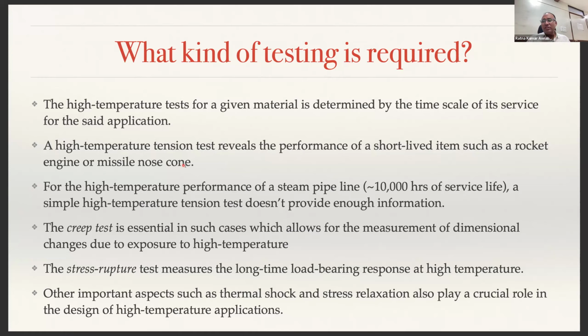However, for example, if you are dealing with a boiler, in the boiler you have a steam pipeline, right? And this steam pipeline is subjected to this high temperature for an extended period of time. Typically, you design these boiler pipes for 10,000 hours of life. Very long period of time. So that means it is subjected to constant temperature and constant load over such a long period of time. Then doing a simple high temperature tension test will tell you only what the strain is at that particular temperature. You are not waiting to see what is happening with relaxation and all these things. So that will not provide enough information. If you do a high temperature tension test in order to design a steam pipeline, that will not give you enough information because it does not talk about creep deformation.